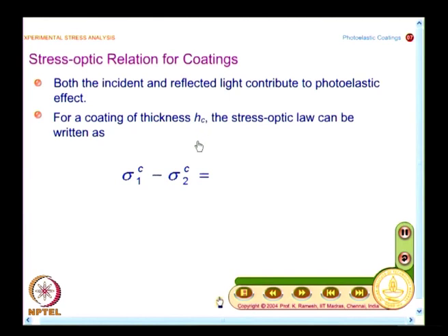because the material that I use is birefringent, it behaves like a crystal when it is loaded. I can also write the stress optic law, wherein I get the coating stresses. Since we are going to have a specimen as well as coating, the symbol used is C, either as a superscript or a subscript, indicating that I am dealing with the coating. And when I want sigma 1 C minus sigma 2 C, if I know the F sigma of the material, then I can write this as N F sigma by 2 H C.